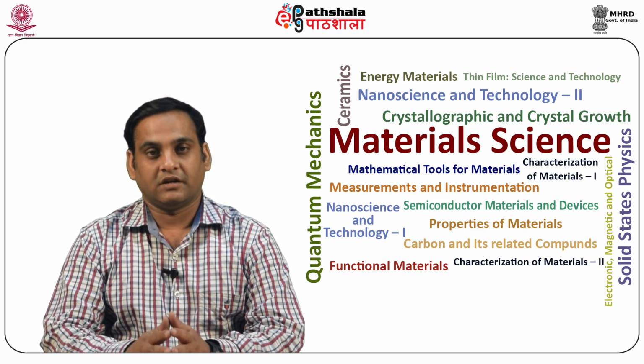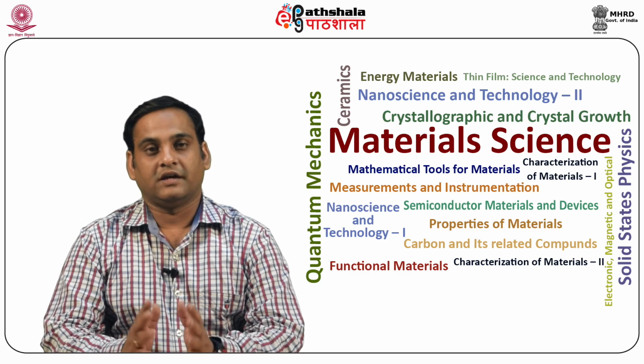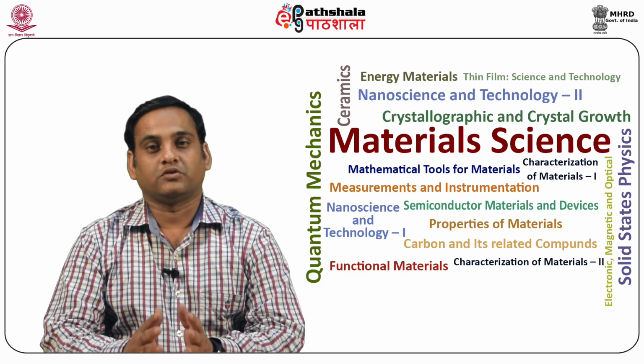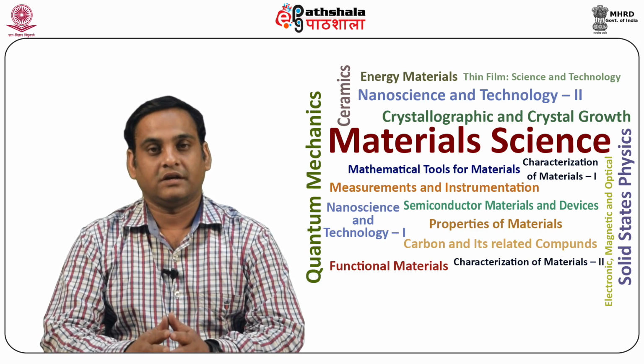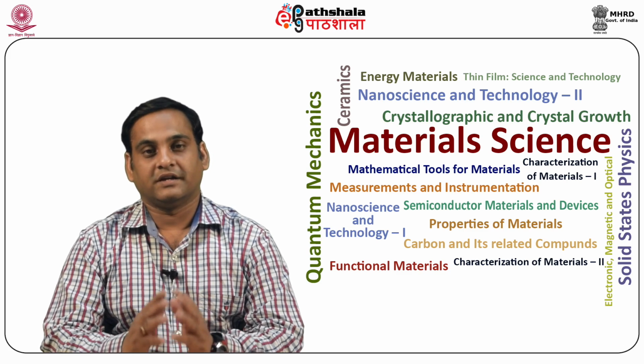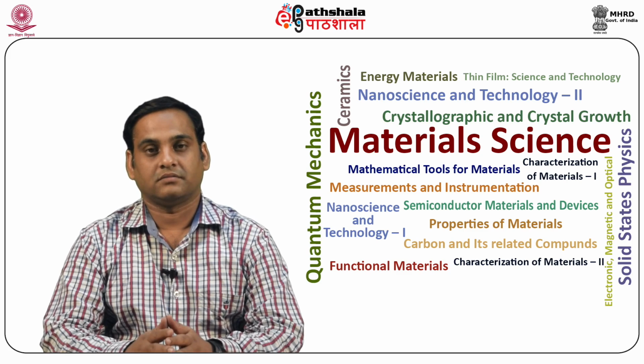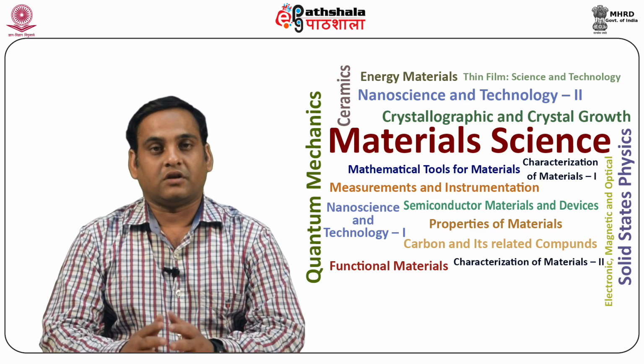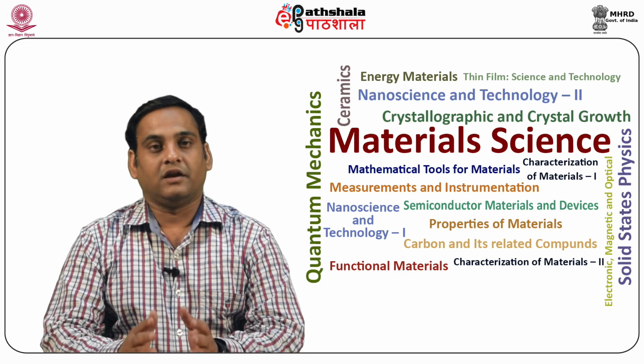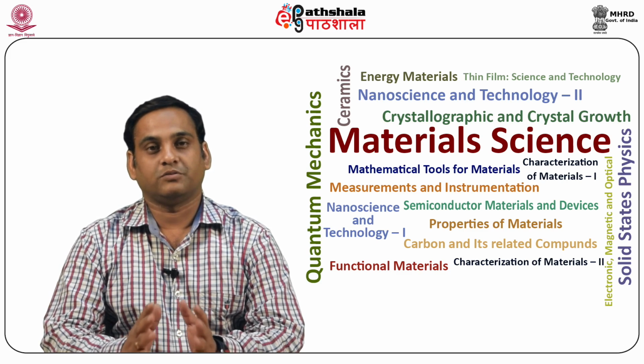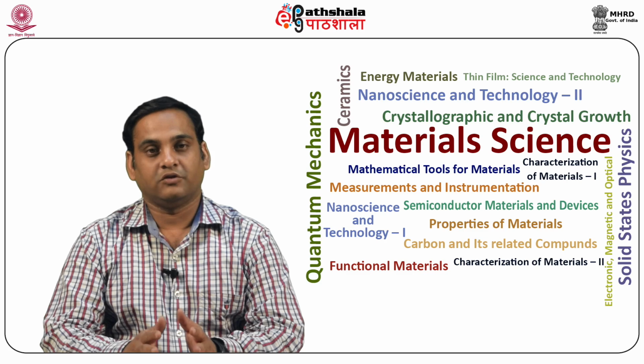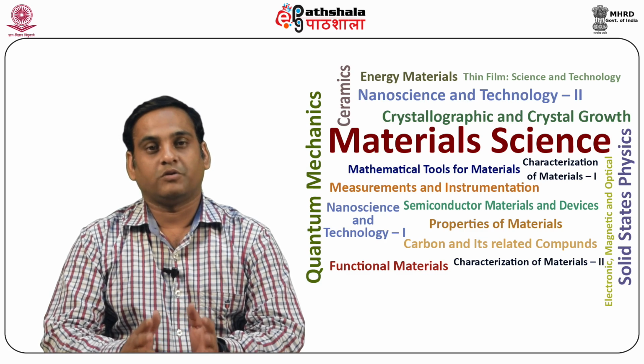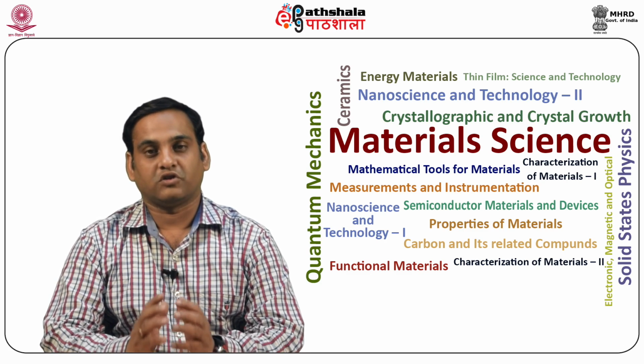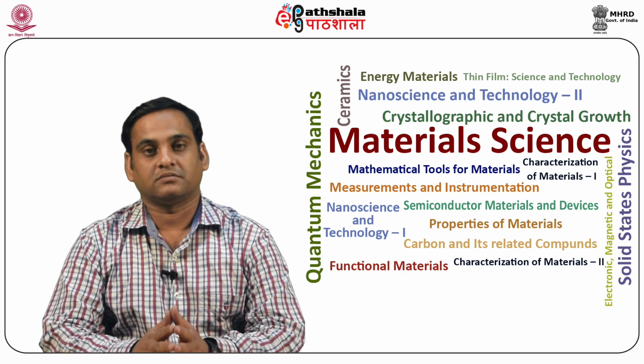Above 120 degrees centigrade, BaTiO3 has the cubic structure as in the figure. When the temperature is lowered through the critical temperature of 120 degrees centigrade, the material becomes spontaneously polarized and at the same time the structure changes. The direction of spontaneous polarization may lie along any of the cube edges, giving a total of 6 possible directions. Along the direction of spontaneous polarization of a given domain, the material expands, whereas perpendicular to the polarization direction, it contracts. Thus, the material is no longer cubic, but corresponds to a so-called tetragonal structure.